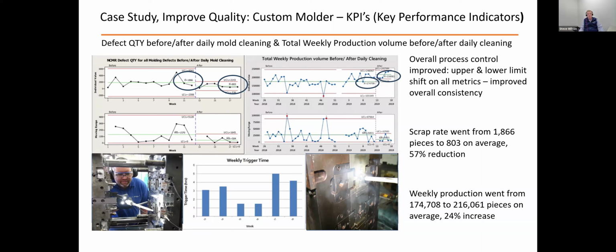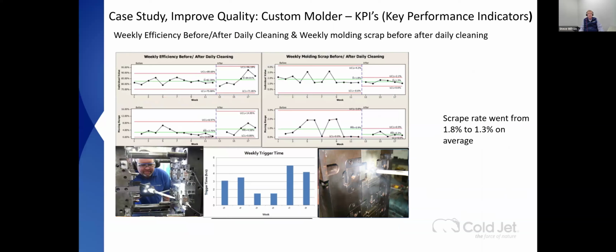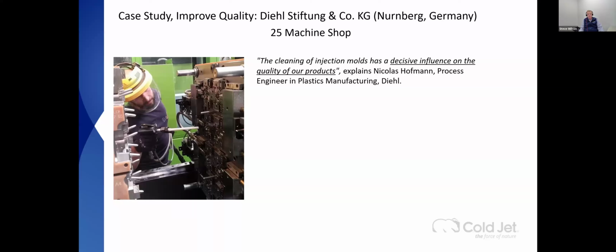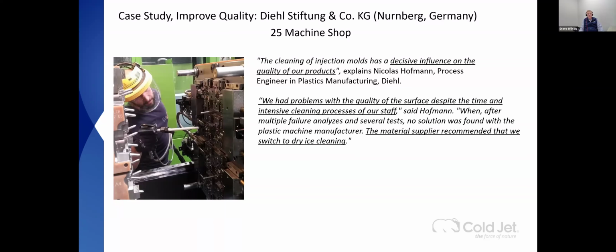The scrap rate went down. They got more good parts, all because they started cleaning the mold consistently with dry ice. That's improved quality cleaning. This is the same guy who's tracking scrap rates. Scrap rate went from 1.8 to 1.3, just because they started cleaning the mold. And customers tell us that. People say it has a decisive influence on the quality of our products.